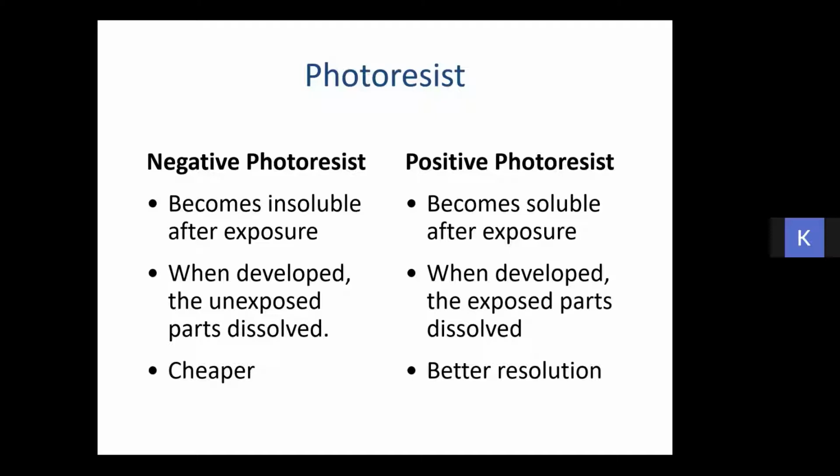However, the best resolution you will get is with the positive photoresist, but negative photoresist is mainly used by people like us who need cheaper technology, because we are not making thousands of devices in a single chip. Our structures are also not always 50 nanometer or 100 nanometer. Our structures are in the range of microns whenever we are doing photolithography. So for that, negative photoresists, which are much cheaper compared to the positive one, are okay for us.